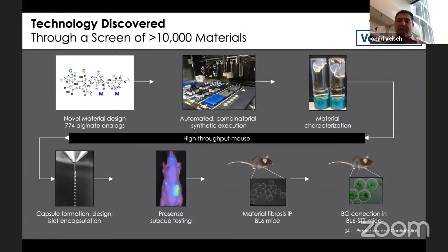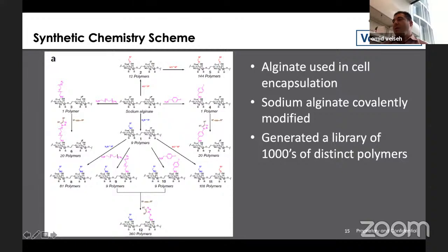We applied the same exact principle to testing all of our formulations, and we could, in parallel, actually test many materials on the back of a mouse that are spatially separated. And we had this ProSense method, which allowed us to quantify the signal, and then the lead materials would then be tested in different implant sites as individuals and also with cells to evaluate whether we could actually achieve better clinical outcomes, better therapeutic outcomes. So this is a bit on the design of the library.